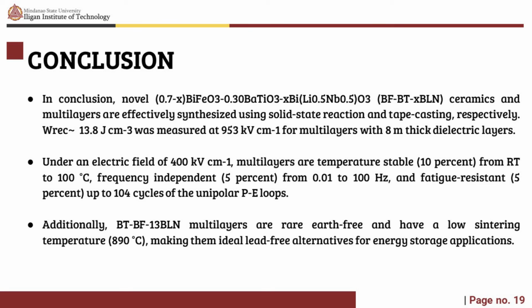Under an electric field of 400 kV per centimeter, multilayers are temperature stable within 10% from room temperature to 100 degrees Celsius, frequency independent within 5% from 0.01 to 100 Hz, and fatigue resistant within 5% up to 10^4 cycles of the unipolar PE loops. Additionally, BT-BF-13BLN multilayers are rare earth-free and have a low sintering temperature of 890 degrees Celsius, making them ideal lead-free alternatives for energy storage applications.